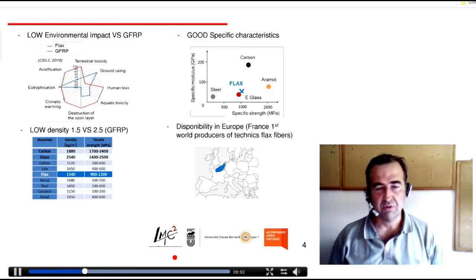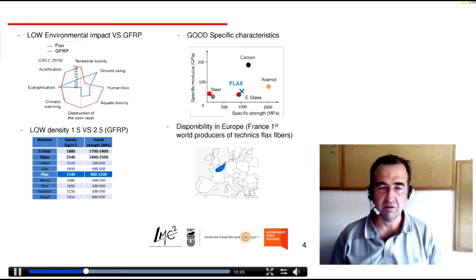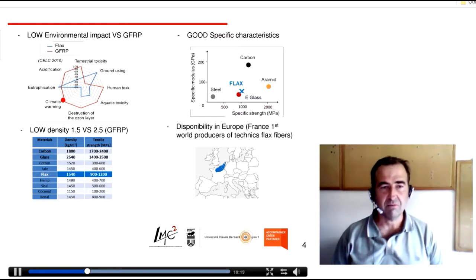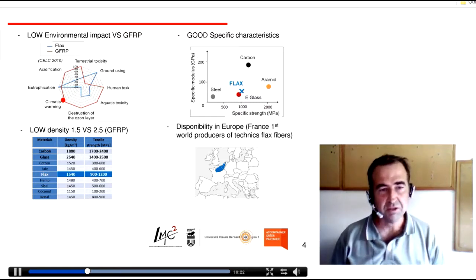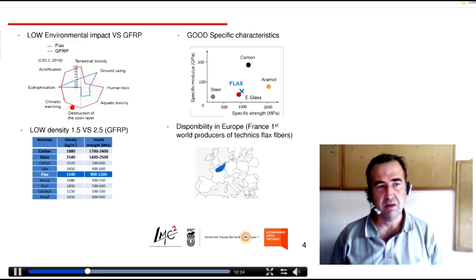So flax fibers, if we compare them to usual fibers, may be mainly compared to glass. If we look at the specific modulus, they are very light, a little bit less high with respect to the Young modulus, but the specific strength is very high. Then, of course, they are less toxic and more friendly for ecology, since they are natural and they are produced very easily.